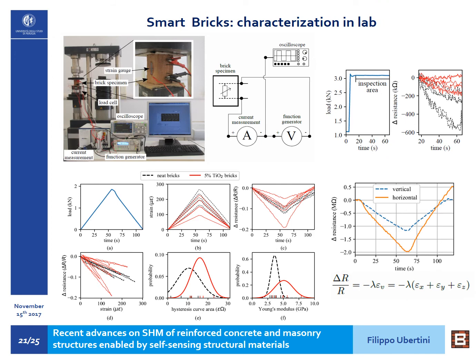So here you see some example of actual compression tests on smart bricks, where you see the application of a triangular load, and again the electrical response of the sensor using the biphasic voltage approach that we have seen before is very much correlated with the load and with the measured strain. What is notable is that with black you see normal bricks. Normal bricks already exhibit some piezoresistive behavior, while nanocomposite clay bricks with red lines are a little bit worse in terms of linearity, in particular because when they are very highly sensitive, they start to exhibit some hysteresis in their response, but they are able to recover the initial value of the resistance after unloading, as you see here, where 5 normal bricks and 5 nanocomposite bricks have been tested.